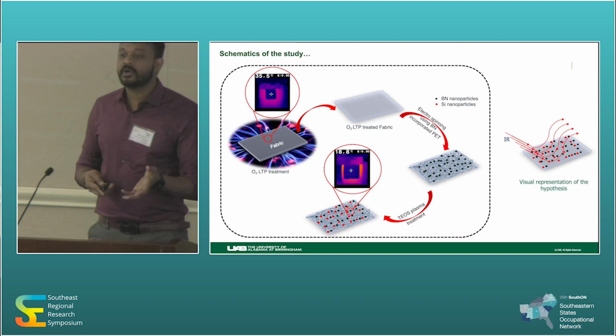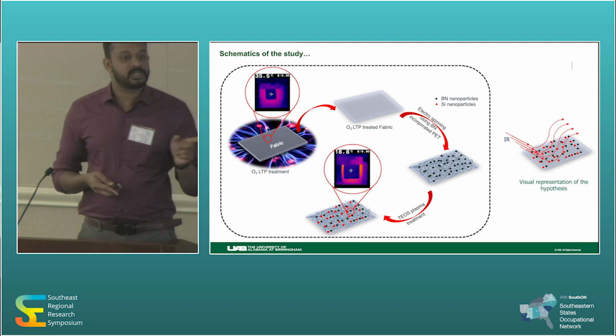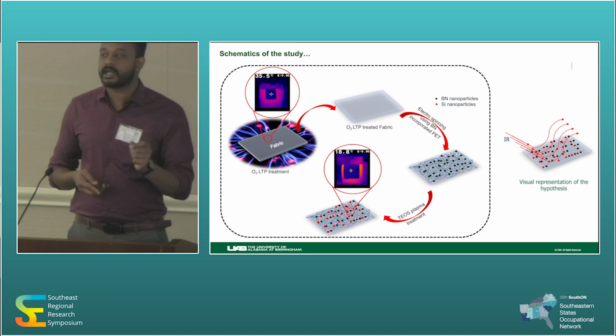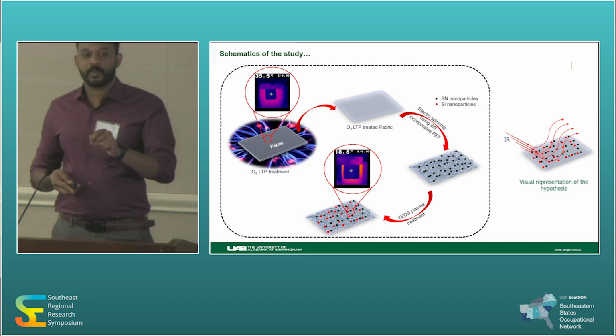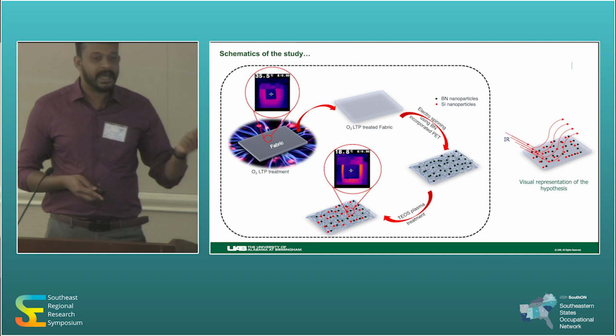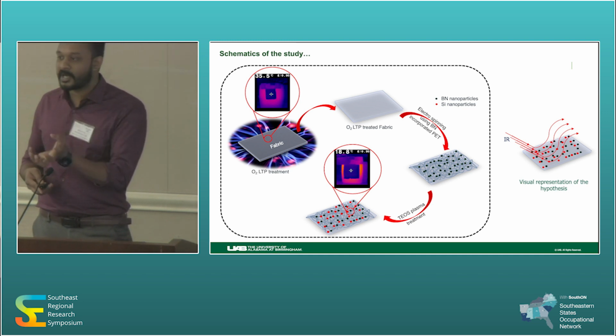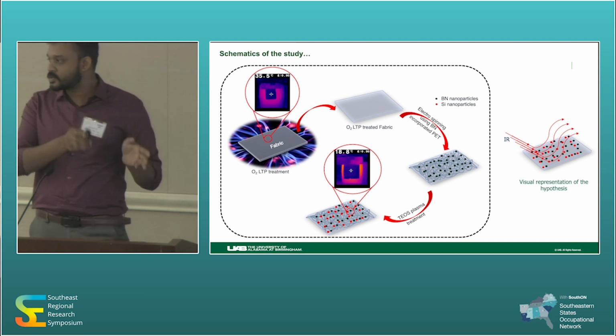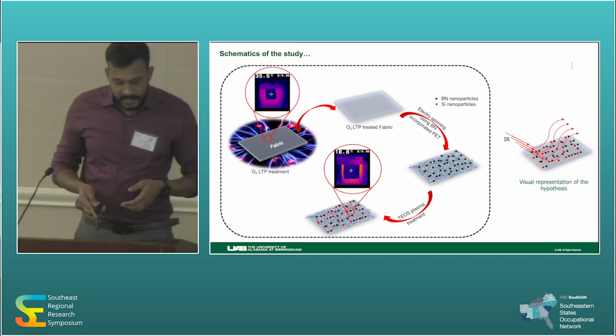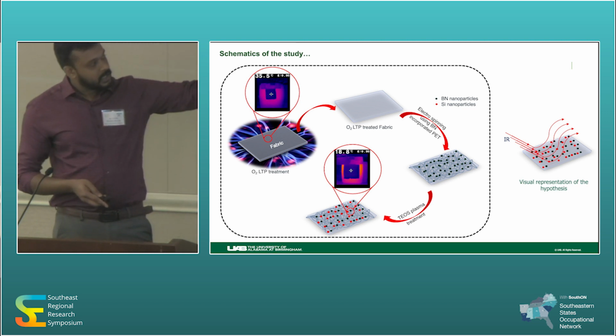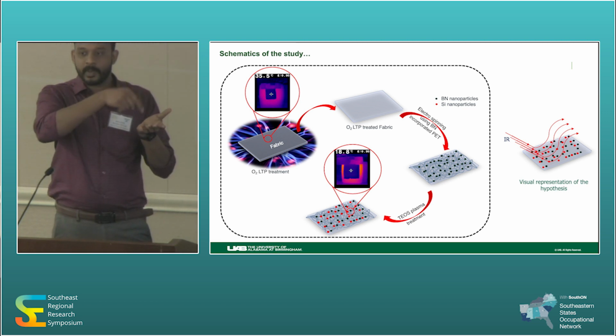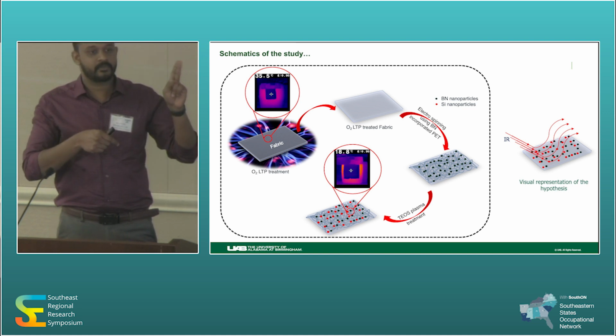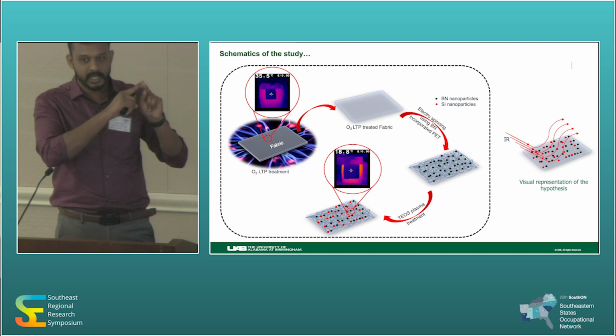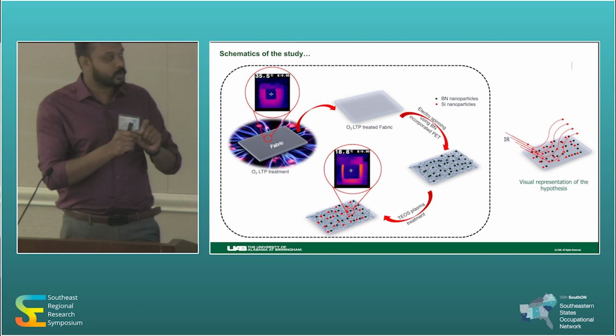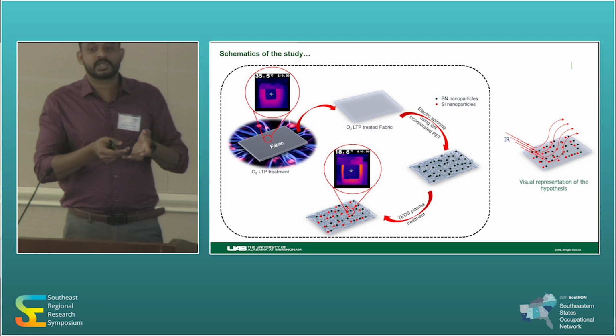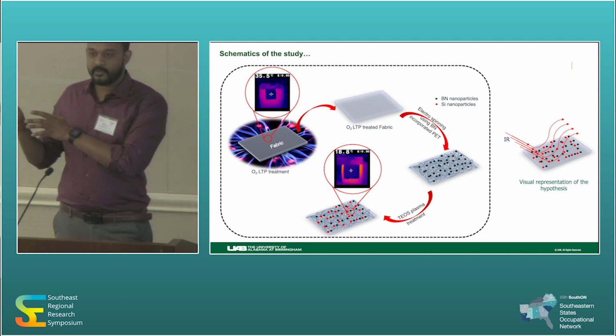Then after that, TEOS plasma, tetraethoxysilane plasma, to create silica nanoparticles on top of the fabric. Silica nanoparticles as well as boron nitride nanoparticles have the capacity to reflect heat. That's what we are making use of in this project. Then there is a visual representation, where on top of the fabric we have the nanoparticles implanted. First is boron nitride, second is silica. Those two have thermal reflection properties, and with that, we can reduce the effect of heat. This is mainly focusing on lab coats.